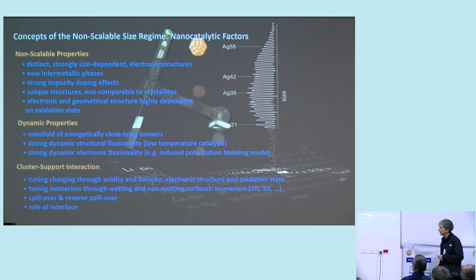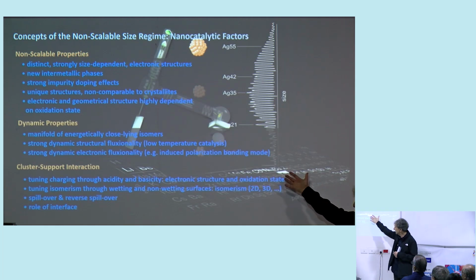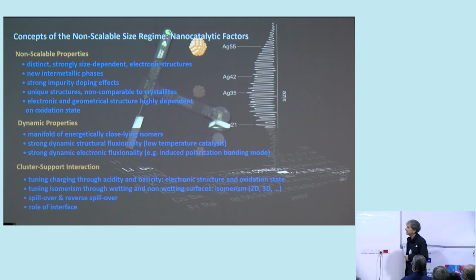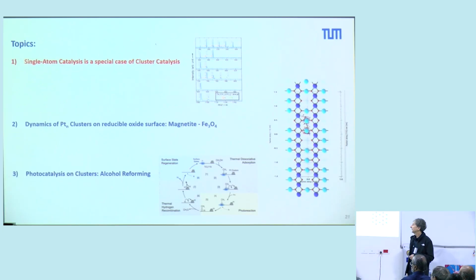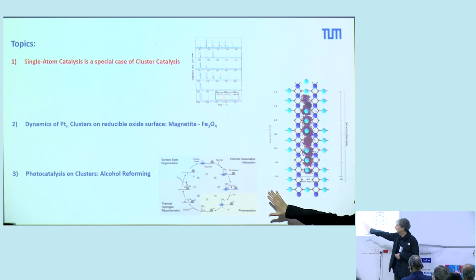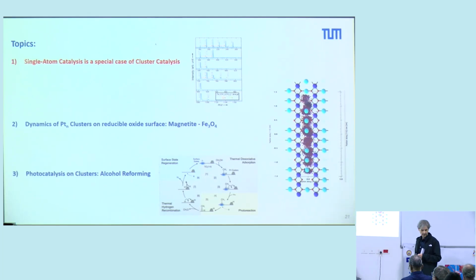And then last but not least, of course, also here we have an interaction with the support material. That means we have this oxidation state we can change. We can change the structure upon interaction with the support materials. And also, of course, we can have this spillover and reverse spillover. So you see that these guiding principles are quite different. Here we expect very drastic effects. And what I would like to do is show you 3 examples. First of all, single atom catalysis, a special case of cluster catalysis. Then I will talk a little bit about dynamics of clusters on surfaces, and then I will talk about photocatalysis.